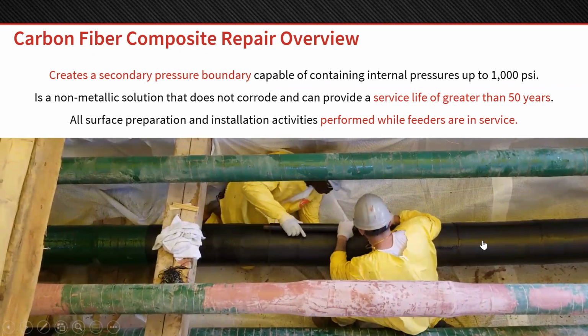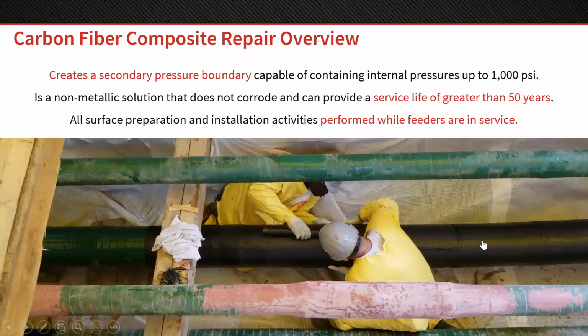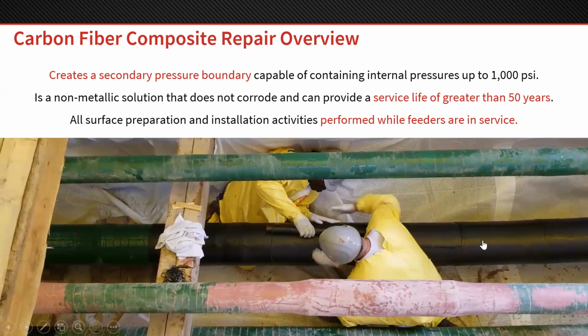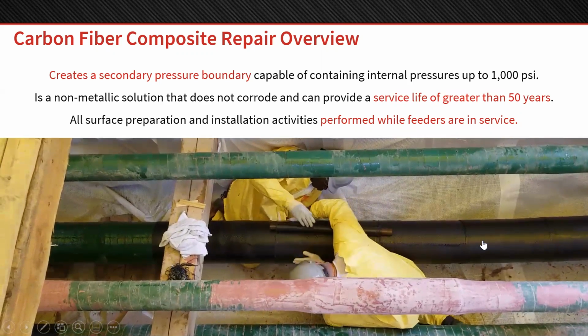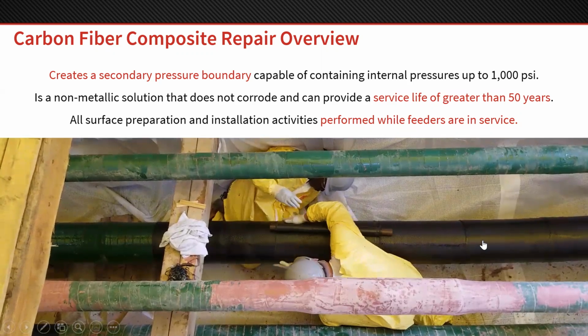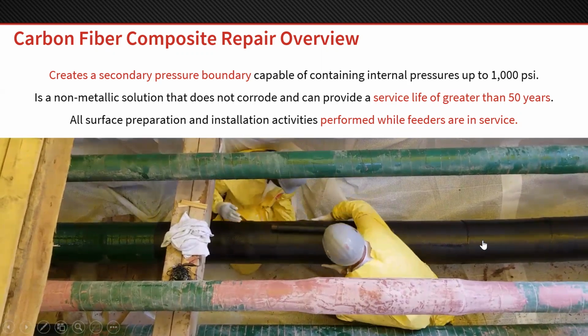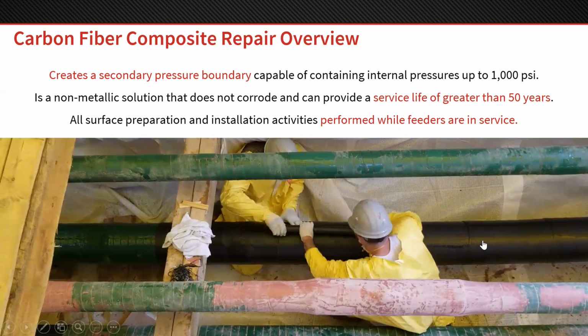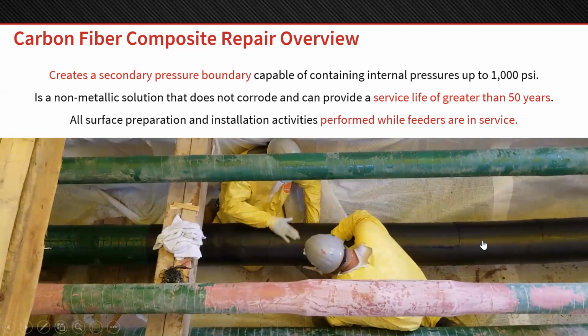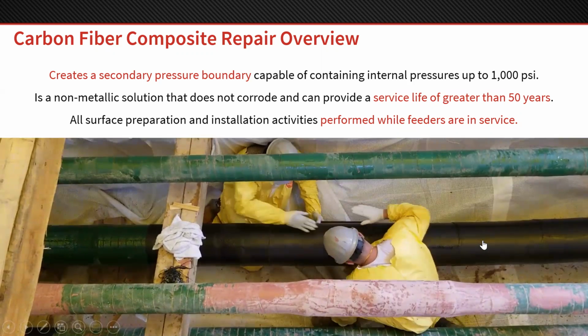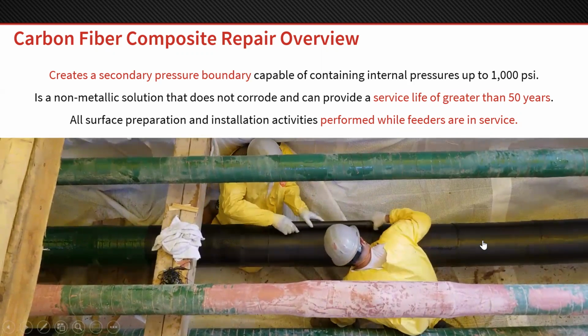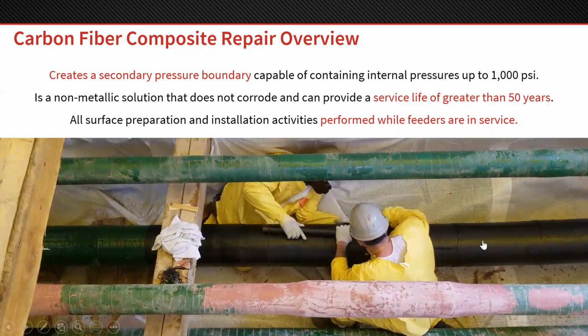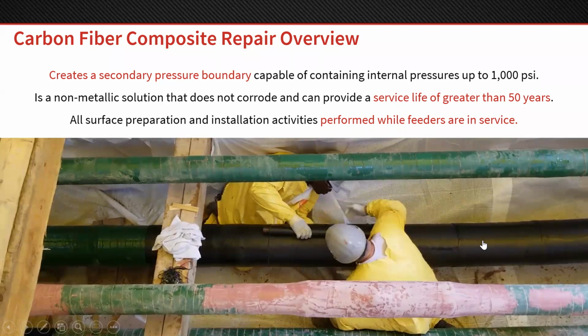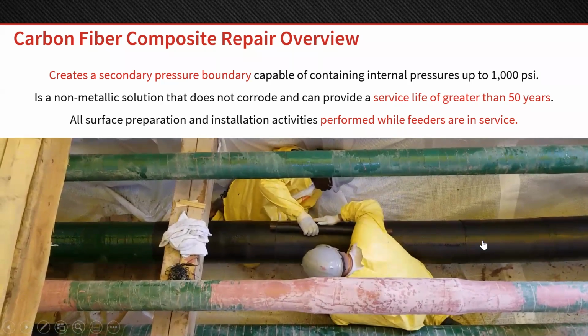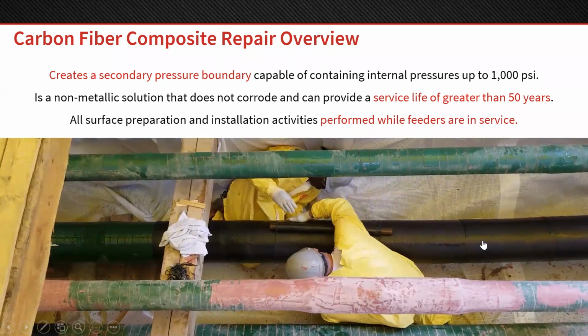The reason that this repair is very different than just a coating system is the carbon fiber is fully structural. It creates a secondary pressure boundary capable of containing up to 1,000 psi of internal pressure. It's non-metallic, so it doesn't corrode as well. So there's no coating system that can fail. This is going to last 50 plus years in the ground without having any corrosion. And these composite repairs are done with these feeders still in service.